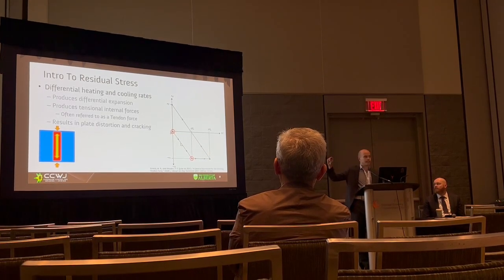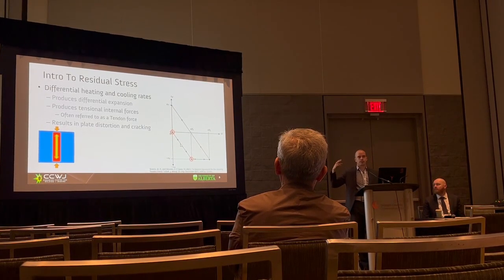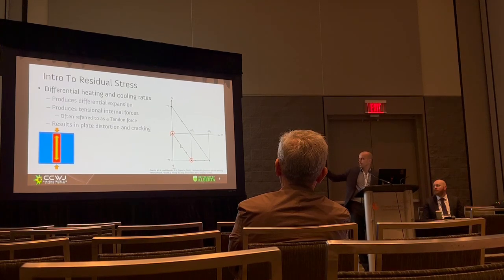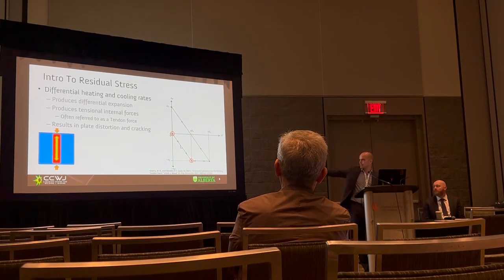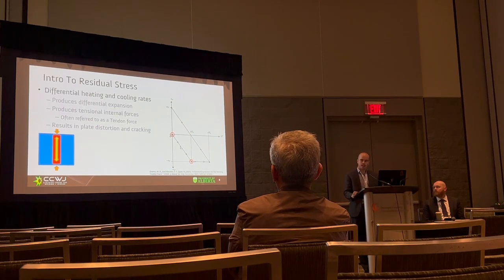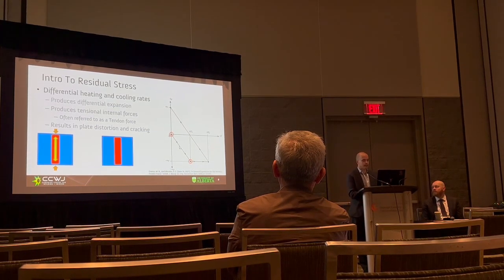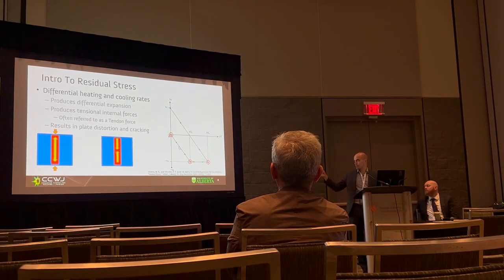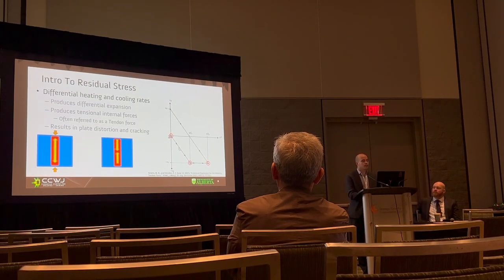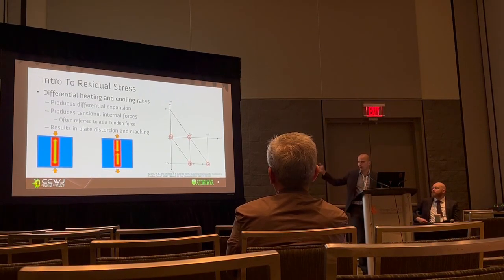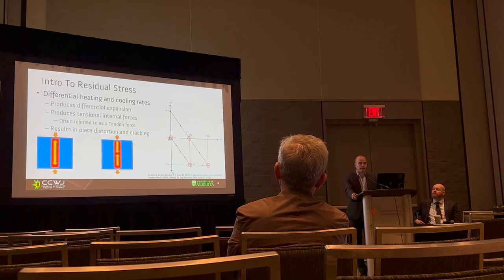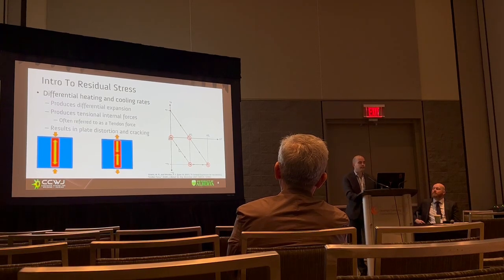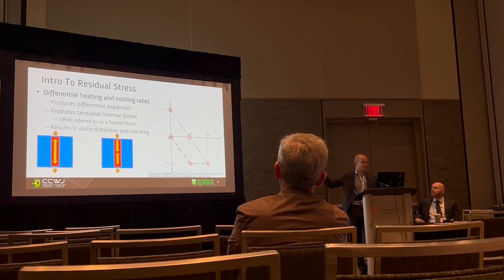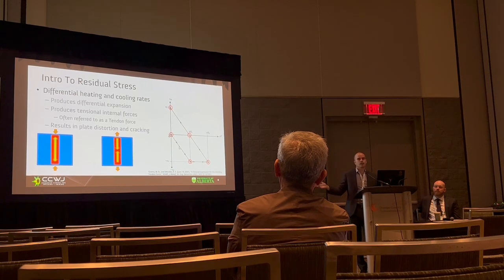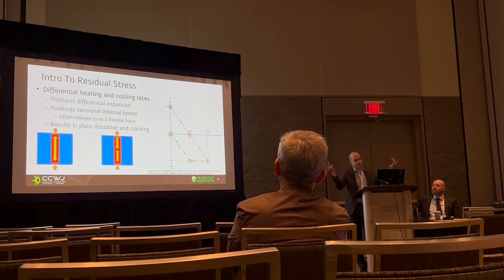Eventually, as the weld gets bigger, constrained by the plate, it's experiencing compressive strain. It's going to keep elastically deforming until it yields, and then that's that second point we just hit. It hits plastic, it yields, and now as it keeps expanding, it's plastically deforming until we get to this point. This is our peak temperature. We start cooling down. Oh no, our weld is bigger than it used to be. When it tries to cool down, it pulls on the plate, and we end up in a very high tensional residual stress. And this is what makes welded plates smile at you.